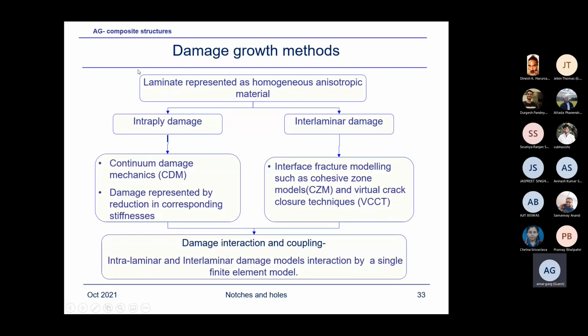Damage growth methods: the laminate is presented as a homogeneous anisotropic material; intraply damage; interlaminar damage; continuum damage mechanics, where damage is represented by a reduction in the corresponding stiffness. I won't go into the details of this. I just wrote some points about damage growth methods and interlaminar damage, interface fracture modeling such as cohesive zone models and virtual crack closure. And these are being pursued a lot. In fact, tomorrow I'll send you some references about this and also these ones. Those who are interested in pursuing further studies in this interesting area, or maybe PhDs, can use it. Damage interaction and coupling, okay, I won't go into.